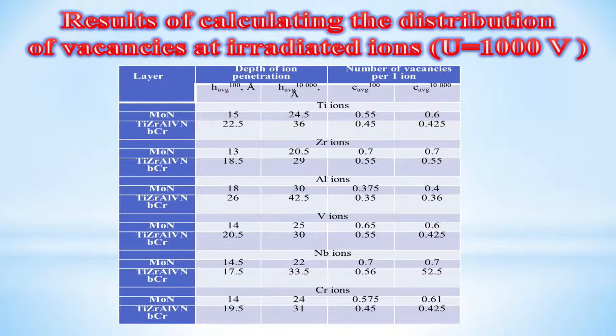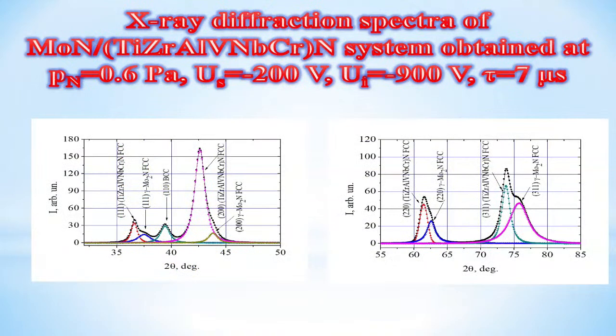On the next slide, we can see diffraction spectra for the multi-element coatings. We can see that in this case, we receive the formation of three-phase state. It is formed from two phases with FCC and one phase with BCC crystal lattice. In this case, the gamma Mo2N phase forms in the molybdenum nitride layers. The hardness of these coatings is about 54 gigapascal, which is higher than for similar conditions in the multi-layer coatings of the TiMoN system. The next slide.